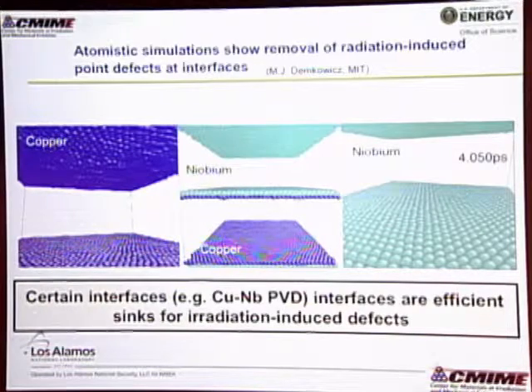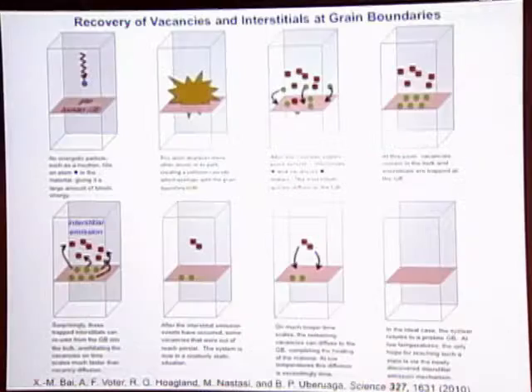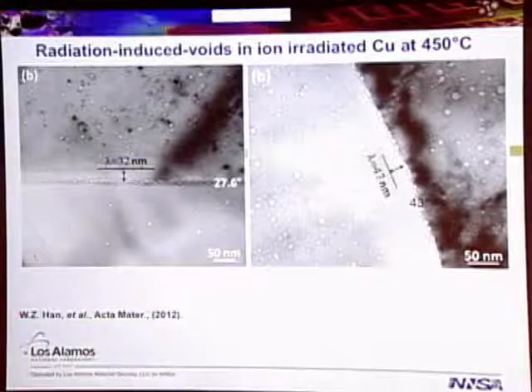And so what we found is that certain interfaces, such as this one that we just looked at, are efficient sinks for radiation-induced defects. Others are not necessarily, and we'll see that here in a minute as well. So let's talk a little bit about grain boundaries, if we're not talking about a composite such as copper and niobium. Again, this process has an energetic particle coming in towards your boundary. It hits your material. There's a whole mess of atoms displacing in the cascade. After it settles, you've got these different kinds of defects, vacancies and interstitials. They move to the boundary. And hopefully, if everything goes well, we end up with a pristine boundary at the end.